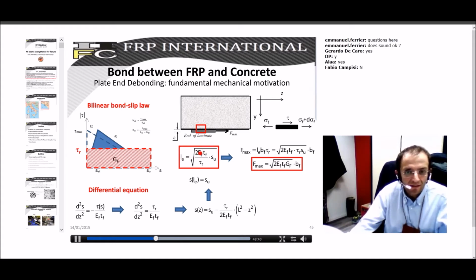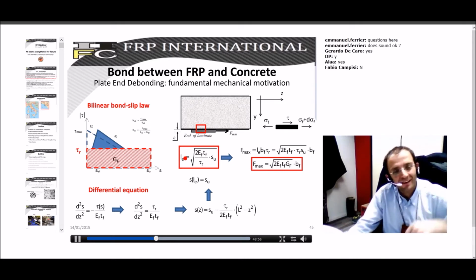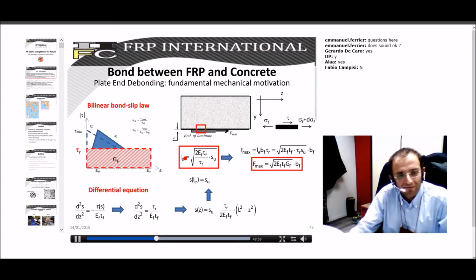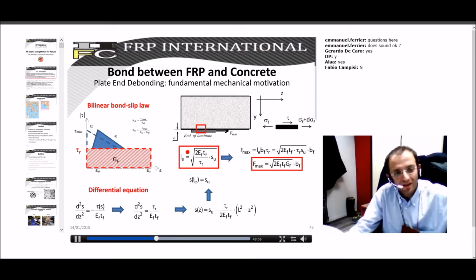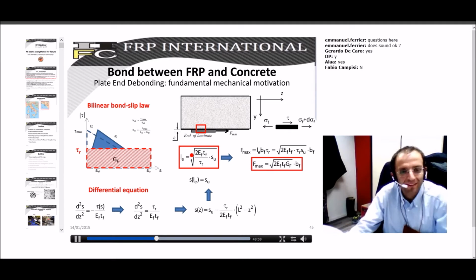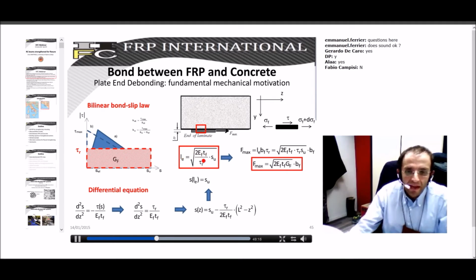As you can see here, you see which are the parameters controlling this LE. So LE is as long as the strip is axially stiff. So if you have a very stiff strip, you have an LE which is a very long one. If EF, TF were infinite, you would have an LE infinite, something like that. If you have a very flexible EF, TF, this would reduce to 0. And at the same time, the maximum force can be evaluated this way. You can just multiply LE times BF times TR in this specific case, and you get this equation.